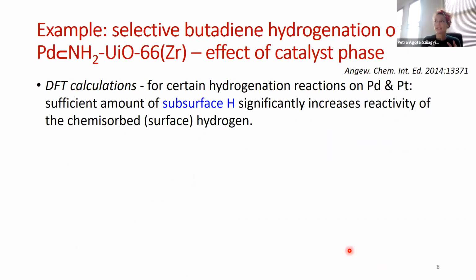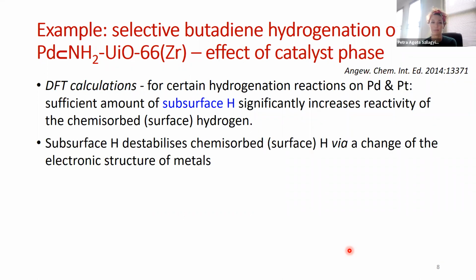But it's not only the physical properties of metals, for example, that change in this very low size regime, but also their chemical properties. And this is what the next example I would like to discuss is about. Our motivation came from DFT calculations originally. It showed that for certain hydrogenation reactions on palladium and platinum, if there is a sufficient amount of subsurface hydrogen, it would significantly increase the reactivity of the hydrogen that is surface adsorbed.